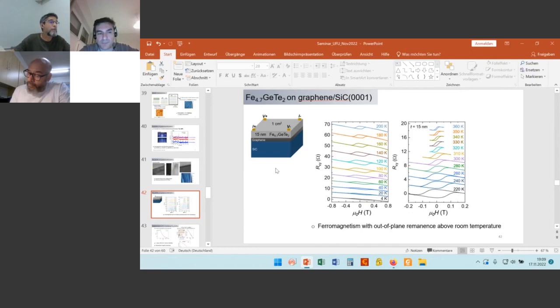Okay, I was surprised when you said that you did measurements on SQUID. I thought you need a big sample, and they are big, so that's why. Well, for the SQUID, you actually need a teeny tiny sample, right? So it's about a few millimeters, 2 by 2 millimeters, but then we cut the sample. I thought it was way smaller than a millimeter, that they were small flakes that you were growing. No, this is really thin film growth. Yeah, that's what we want to go for.